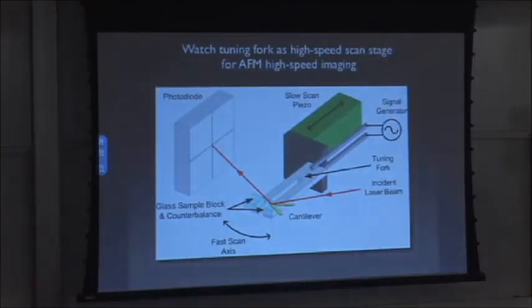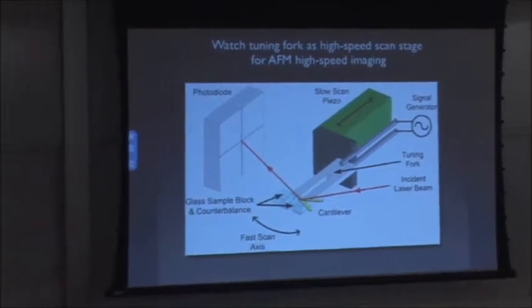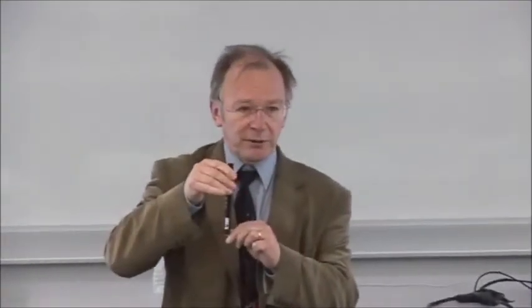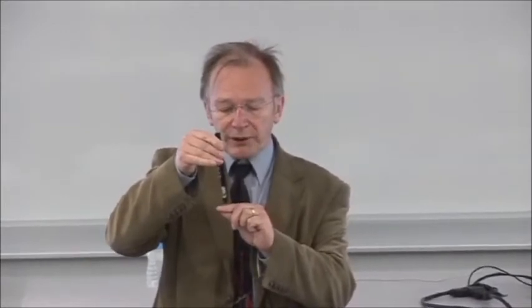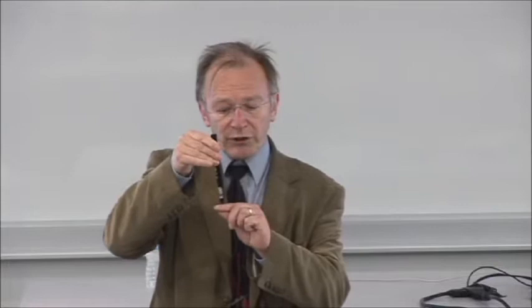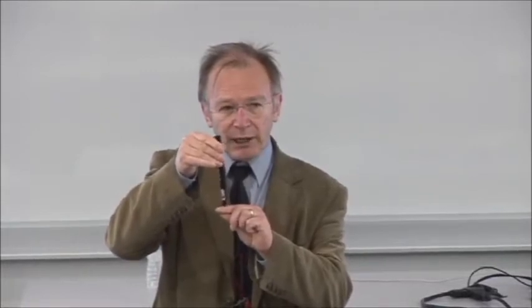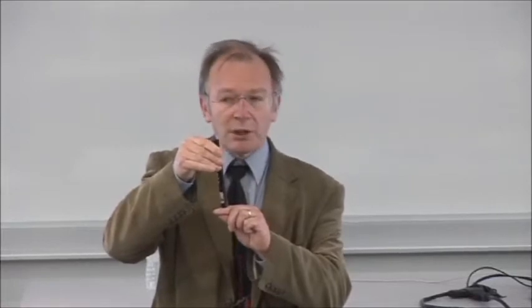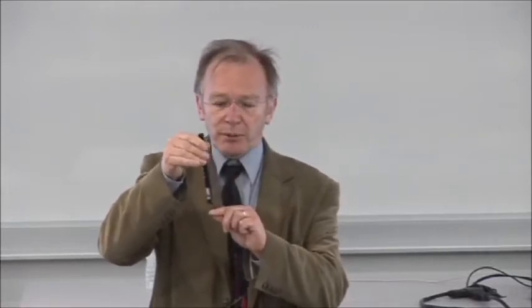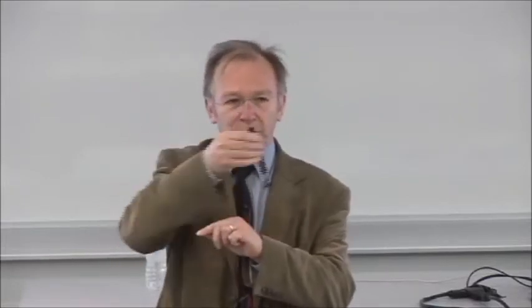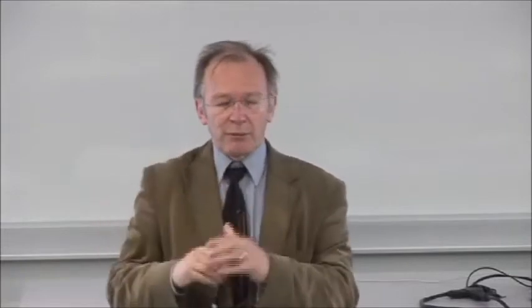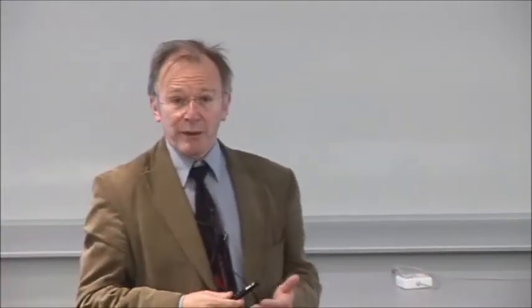This is how we started. We started actually doing high-speed near-field optics, where you oscillate an optical fiber, coated with aluminium, with a small aperture, and you bring it into the near field, very close to the sample, and you get resolution beyond the diffraction limit. What we were doing there was controlling the distance by this shear force, oscillating our fiber, feeling the surface before we touch it, actually through layers of water molecules. And then we invented a high-speed version of that, where instead of just dithering this little probe by a nanometer, we actually whacked it up to microns and just collected the data. We were able to get 100 frames per second compared to 1 frame every 20 minutes. So that was a useful breakthrough.